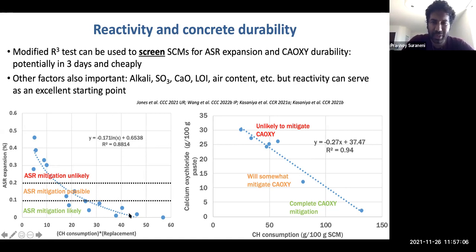And you can kind of classify materials which will likely mitigate ASR, materials which are extremely unlikely to mitigate ASR, and materials where really you need further testing. So these materials, and these were largely limestones or other inert materials, these will not mitigate ASR. There's just like literally no chance. These materials, on the other hand, these are very reactive materials, pumice, fly ash, etc. These will most likely mitigate ASR.